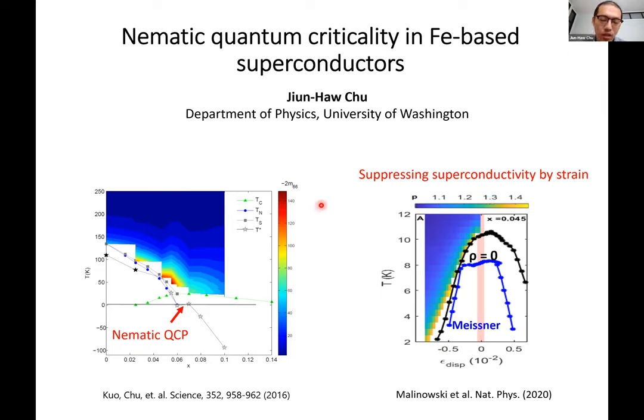What I am going to talk about today is a story about two remarkable findings near the nematic quantum critical points of the iron-based superconductors. The first one is that we find the superconductivity near this nematic quantum critical point is extremely sensitive to strain. It's so sensitive that, for example, for this underdoped compound with a 13 or 11 Kelvin Tc, you can fully suppress the superconductivity. The Tc can extrapolate to zero within 1% of strain. Obviously, this has something to do with nematic quantum criticality, but it also implies that there is a very strong electron-lattice coupling in this material.